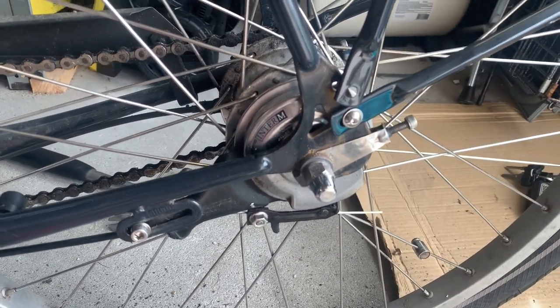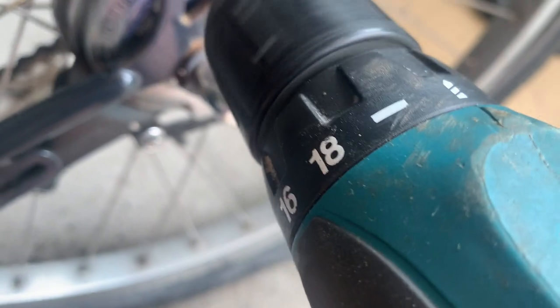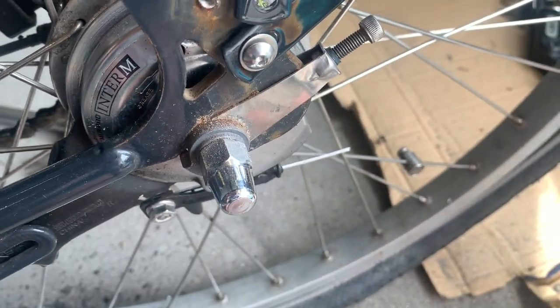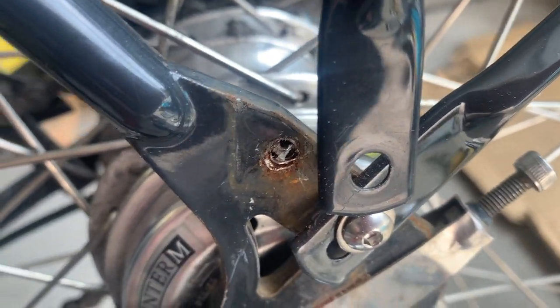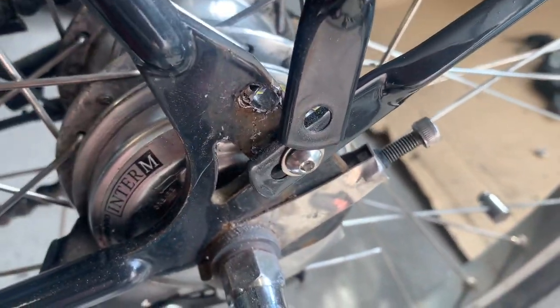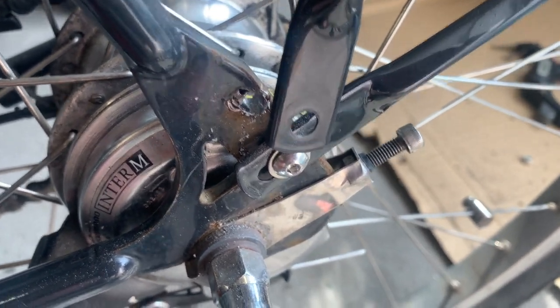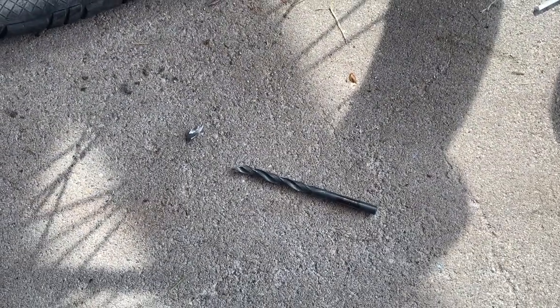Let's see if we can drill it through easily — you should probably not do this with a power drill. To me that looks like it's going to work. I tried to rerun the tap once more, and now there is a piece of hardened steel stuck in the frame. What did we learn? If you're going to tap a hole, make sure the hole is the correct size. I drilled this hole too small when I tried to tap it — that's why the tap broke. And hardened steel is no match for cheap drills, basically. But there's a hole in there now.